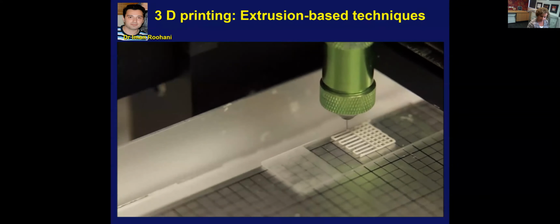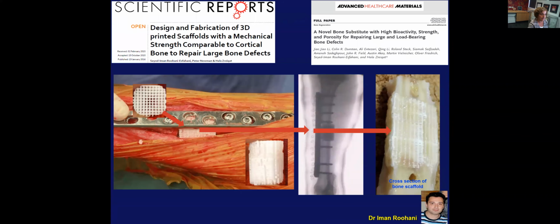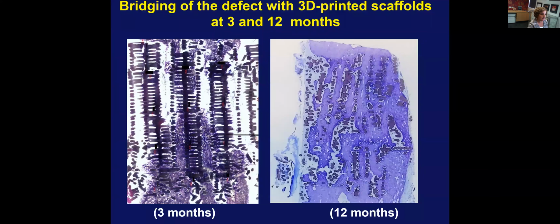So we printed this material, and then we implanted it, and we validated that the mechanical strength of that material at the high porosity and interconnectivity matches that of cortical bone. We then implanted it as is, no biologics, autoclaved and press fit into the defect, a tibial large bone defect in the sheep. And at 3 months, you can appreciate that the material maintained its mechanical properties. When we looked at 3 months and 1 year, these black areas are the struts of the ceramic. This is new bone growing into the ceramic. You can see bone growing from the edges of the defect. And by 12 months, we had the defect completely bridged with new bone.